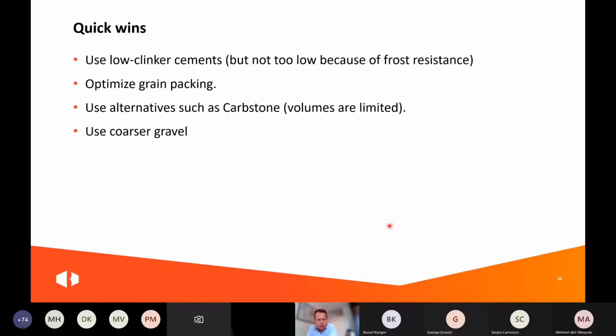But what we can do is, of course, use low clinker cements as far as possible. But of course, don't go too low with your clinker content because we need the frost resistance for our roads. Optimize grain packing. I really think that can save, if you do it very well, 20 to 30 kilograms of cement per cubic meter or even more.